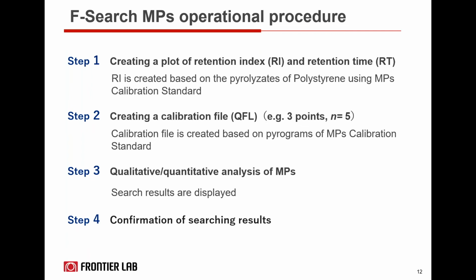Step 1 is to create a plot of the retention index and retention time, where the retention index is based on polystyrene fragmentation. Step 2 is to create the calibration file that is based on the pyrograms of your microplastic calibration standards. Step 3 is the search results of microplastics. And then step 4, which I find very important, is the confirmation of the search analysis that you just obtained from F-Search.